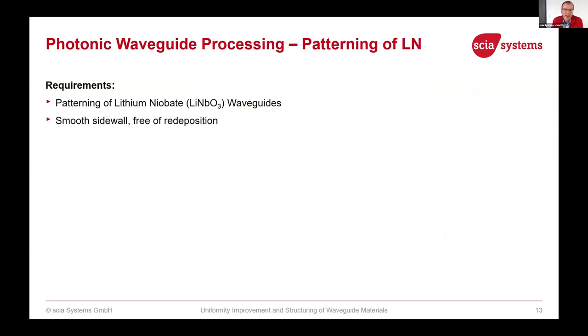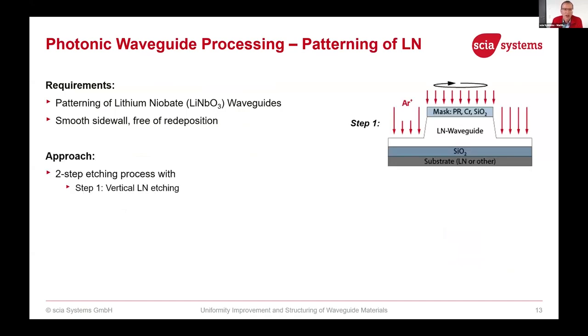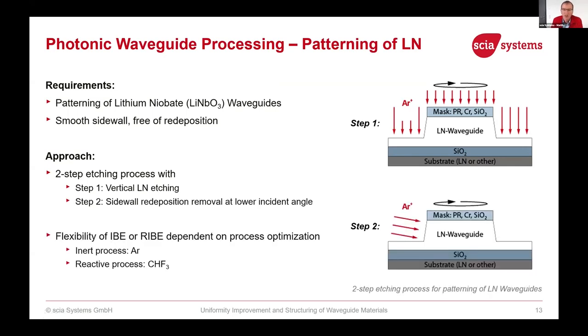For patterning of, for instance, lithium niobate waveguides, we have some requirements like smooth sidewalls, and the sidewalls should be free of redeposition. And therefore, we have a two-step approach. In the first step, we etch perpendicular, means we etch from the top through our mask into the lithium niobate and create the waveguide while we rotate the substrate, the wafer. And then for keeping the sidewalls clean, we tilt the wafer to a certain angle of, let's say, 70 degrees. And then we hit this side of the structure with an argon beam to clean it up.